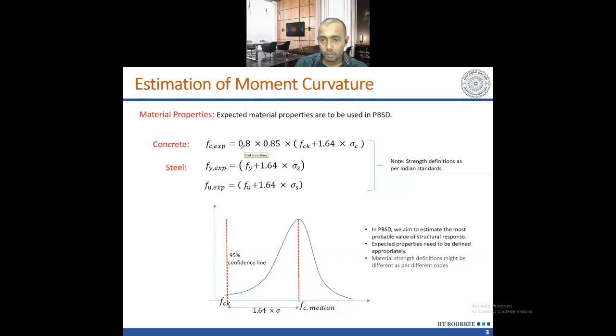Now here only this term FCK you have to take care of with respect to your country code. Similarly, you have the expected strength for steel. Fy is the defined value as per code. For example, Fe 500, which is 500 MPa or 500 Newton per mm square grade, again you add 1.64 into sigma, a similar standard deviation value. But here you do not get these factors, because in case of steel, whether you take a small specimen or a large specimen, the strength will be the same in all cases. So these factors do not come here. Similarly, for ultimate strength you have a similar expression. So you use this expression to determine the expected material properties.